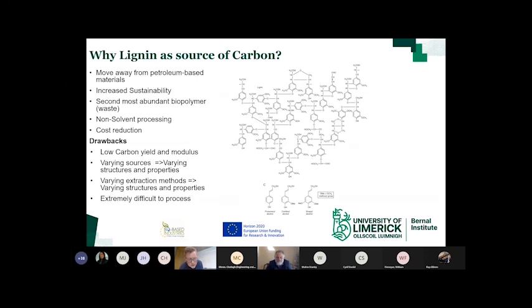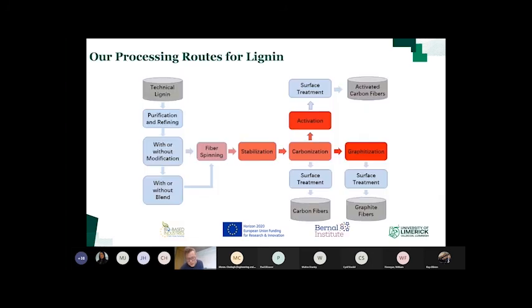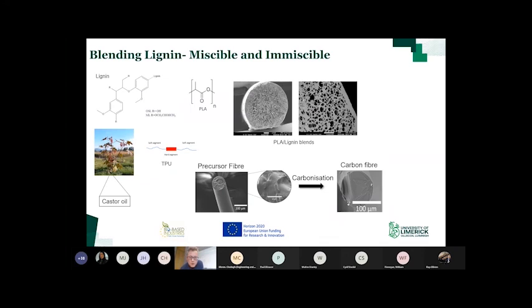Just one sec. So you might be wondering, why have people not used lignin up to now? Well, that's because there's a low carbon yield, it's from varying sources, and it's extremely difficult to process. And that's where I guess we've made our breakthroughs. So this is for people familiar with carbon fiber. You can see that this is the processing route that's used. Our main breakthroughs have been in the stabilization part, where we've been able to stabilize our materials faster to allow carbonization. So we've produced two types of carbon fibers. We produce porous fibers for functional materials, and we produce non-porous fibers for structural applications.